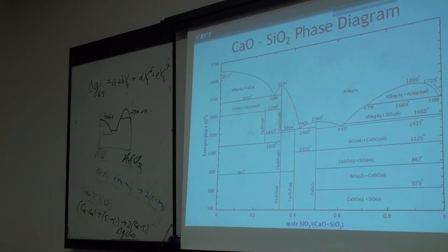The reason is, with the Redlich-Kister, which would be something like x silica minus x calcia to the 6th, it would have an effect on both sides. It's symmetric around 50%. You're trying to fit this and you'd be messing up this side. These terms here only really affect this side. Besides, you want these terms to have something to do over here, so you want a high power. So this is generally what we do in these systems.